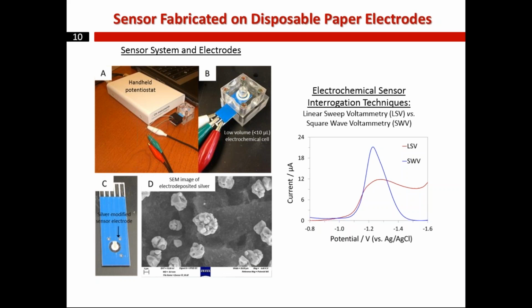However, although these sensors appear to be selective enough to determine nitrate in the real world, since we are talking about microelectrodes, you might think that using these microelectrodes in the real world might not be very practical. So in order to address this issue, we tried to see if the same idea can be applied onto a disposable paper electrode. The paper electrodes that you can see pictures of over here are a type of relatively cheap and commercially available electrode that can be run with a handheld potentiostat. So therefore, you can say that these types of electrodes can be easily used for detection of nitrate in the real world. So we technically applied the same idea here.